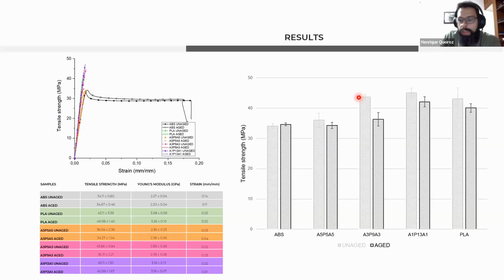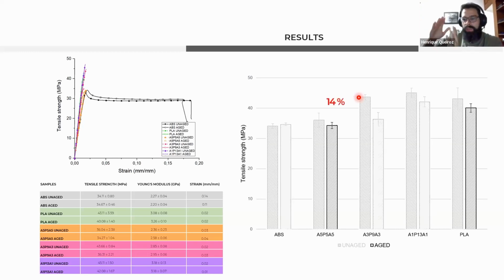Now, interestingly, if you look at the aged specimens, we have the same behaviors, two plateaus, but we've essentially moved one case over with a variation of approximately 14% in tensile strength. Now, the reason for this is likely because this is the aged group, right? So the PLA that was in the middle got deteriorated more than the others, of course. And so it took more PLA to reach the same plateau, right? And it's not graphed here in bar chart, but you can take a look at the Young's modulus here. And you can see as a function of the aging, there was actually very small variation here, which makes sense when we look at the behavior. So the final strength was the thing that was most affected and not the actual rigidity.